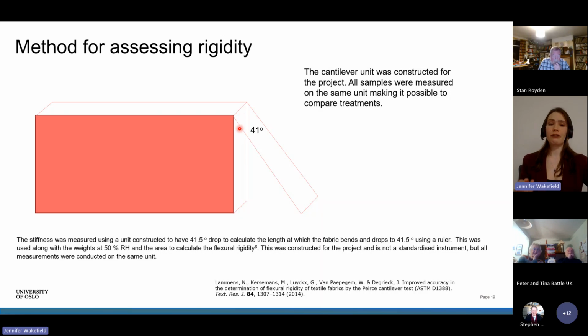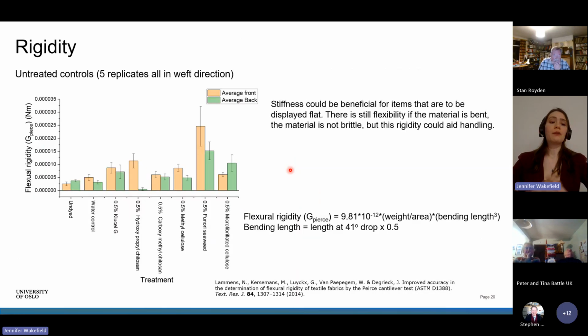If it's very, very flexible, the second you push it off the edge, it will drop onto that 41-degree angle. The stiffer material, you'll push out further before it starts to bend and drop. So that's a way of assessing the stiffness. These are the results from that. This flexural rigidity also takes into account the weight and the dimensional area as well as that bending length, so that you're not having any bias from the exact size of the piece that you cut.